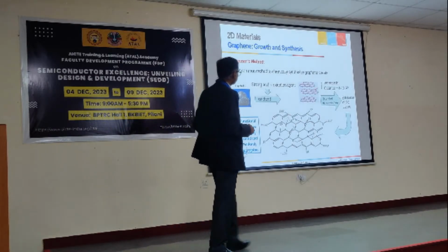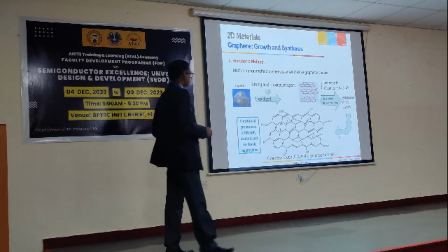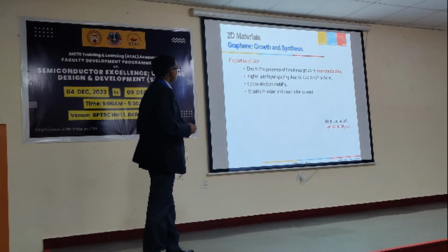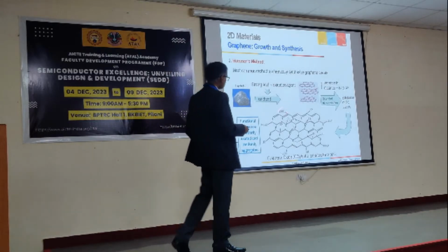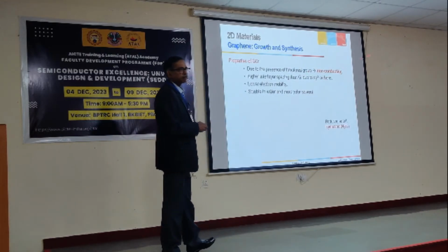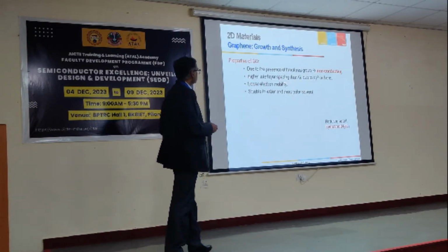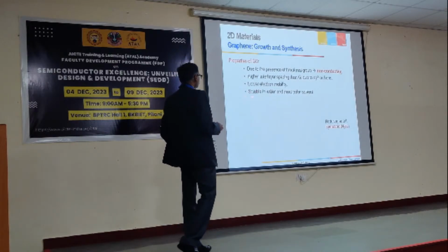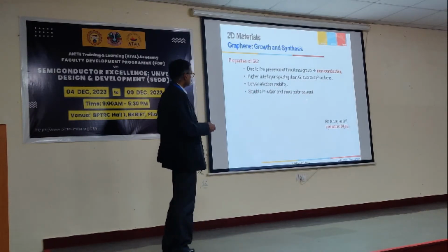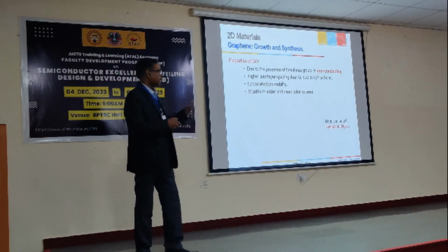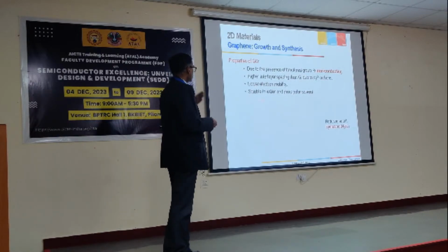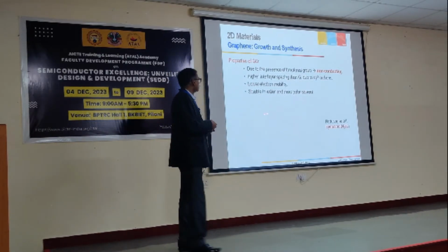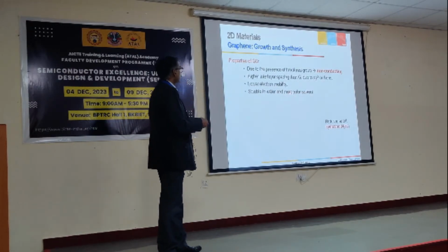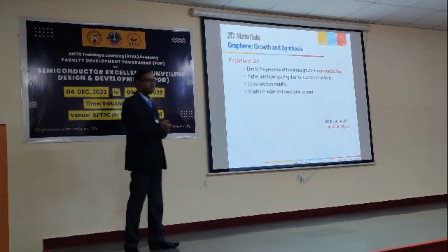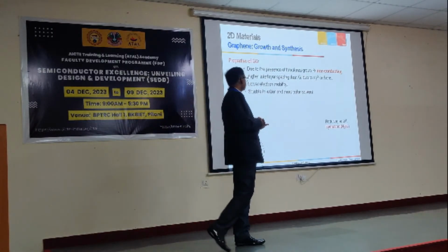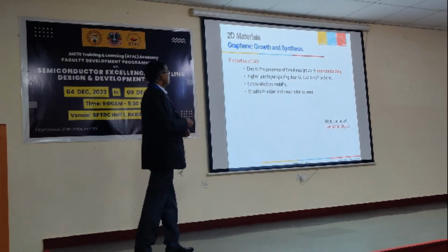So what are the problems associated with this graphene oxide? Due to the presence of these functional groups, these hydroxyl and other groups, it is non-conducting, and also you have a higher interlayer spacing, and the mobility is very poor. It is soluble in water and most polar solvents, which is not desirable, because once you place it on a substrate, the device may undergo various other fabrication steps, so it should not be soluble in water. And also you have a lot of other agents there for the processing. So these are the problems associated with graphene oxide.